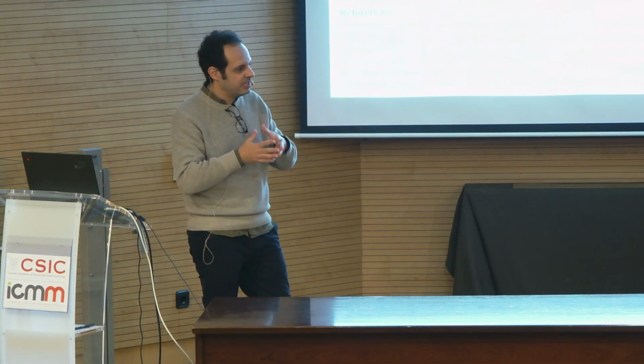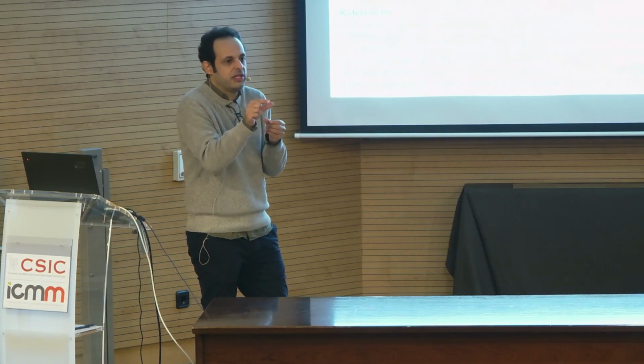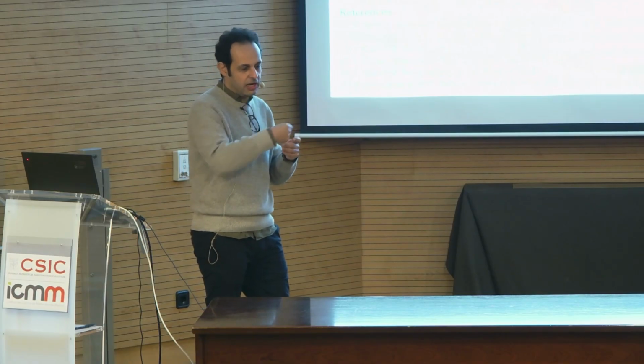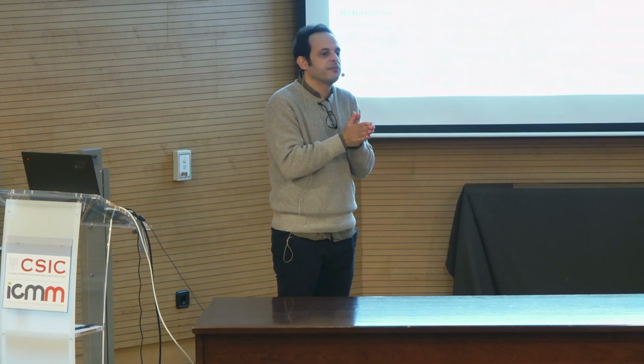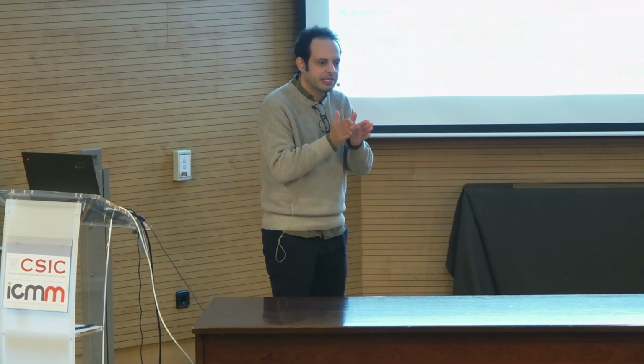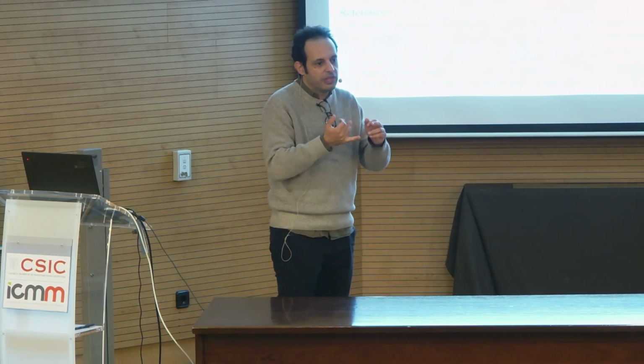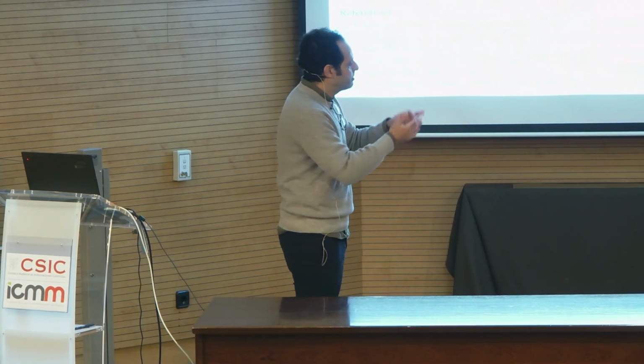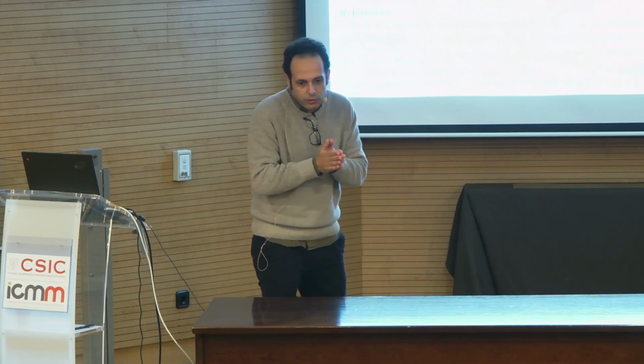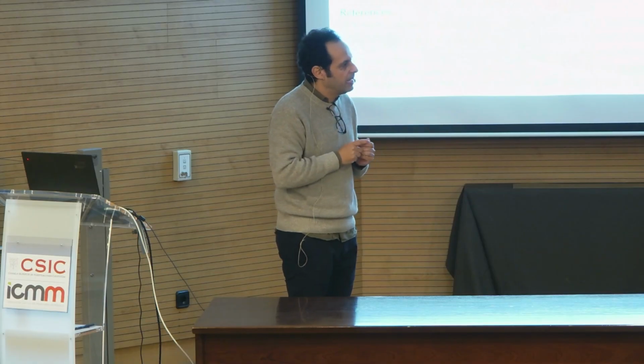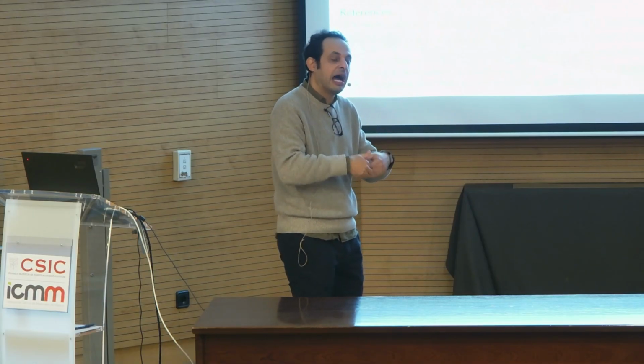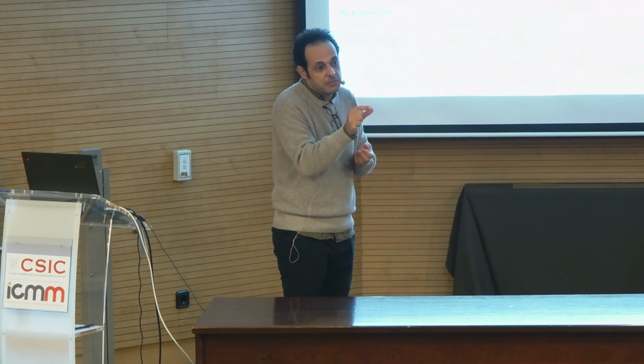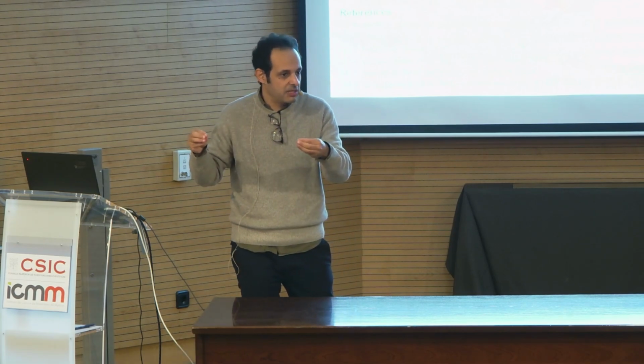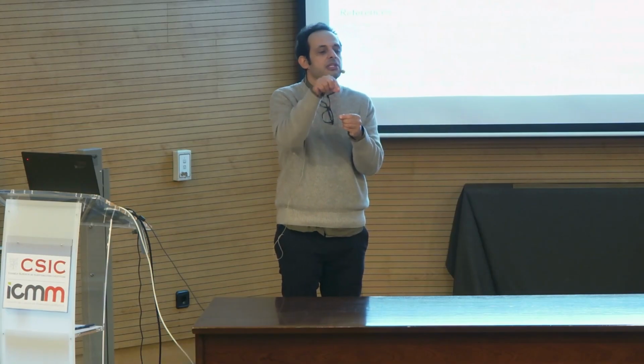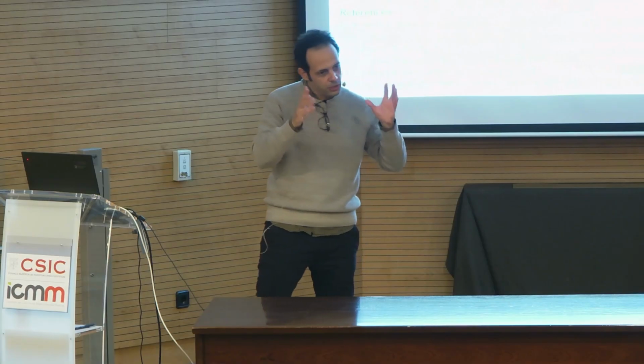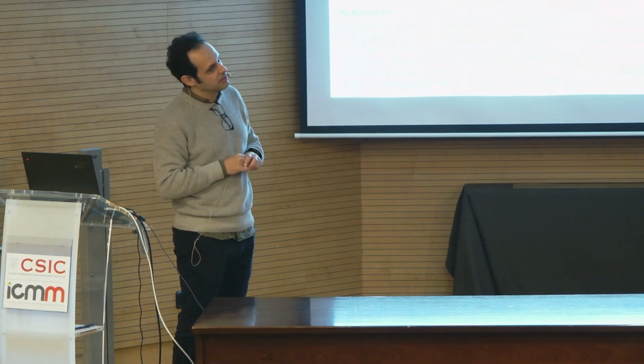Okay, and the fact here is that depending on the characteristics, for example, of the neck size or the diameter that we choose to pattern our materials, we get completely different results in terms of heat flux. So this has to be related to the characteristic length scale of the material, related to the phonon mean free path in the material. It doesn't mean that, for example, in the tin diselenide that we work with, the specific pitch we use for our holes is universal. If we go to a material that has a much higher thermal conductivity, this pitch might be different because it has to be related to the phonon mean free path, and the phonon mean free path is changing. So if you think of these holes as scattering centers, you will somehow conceptualize all this work.